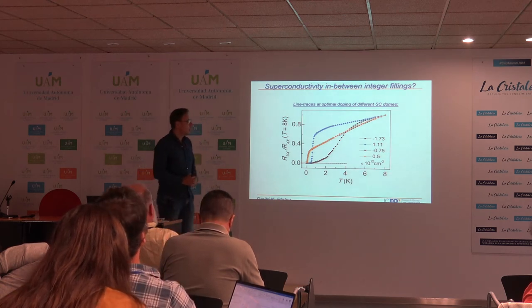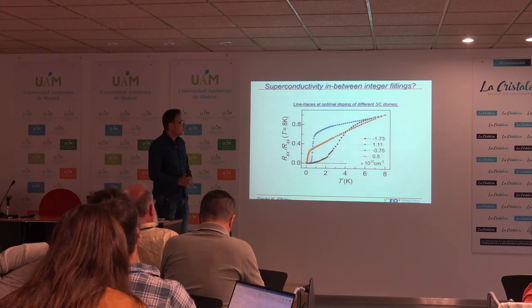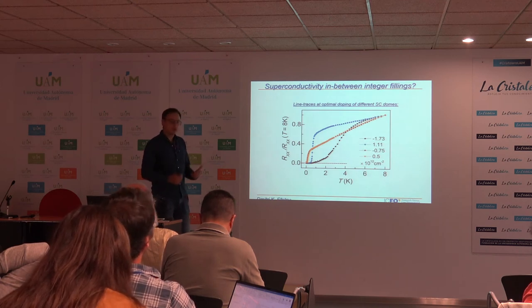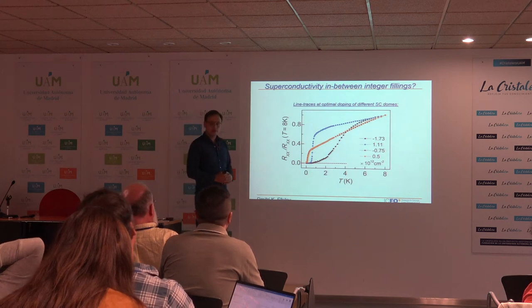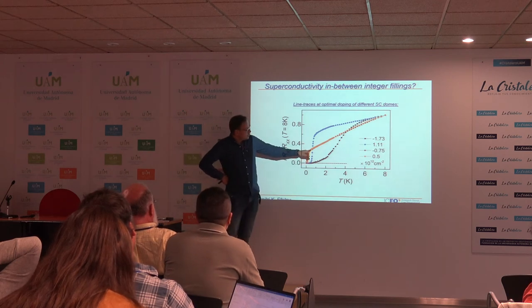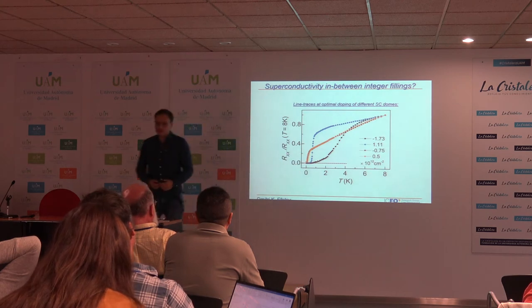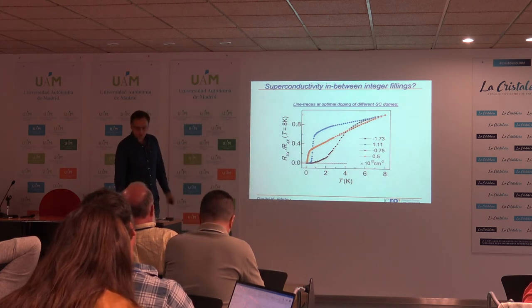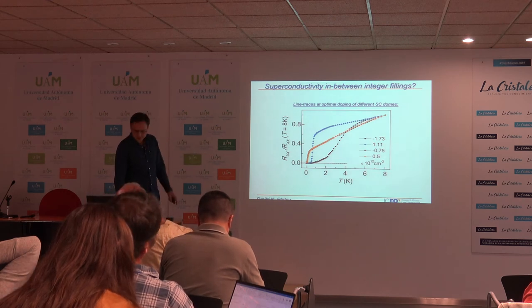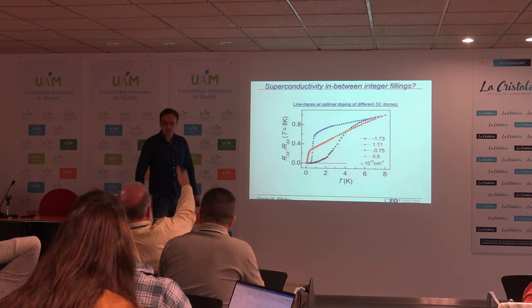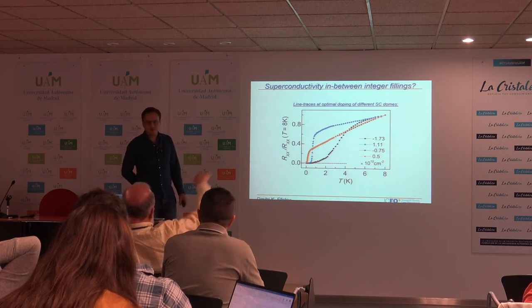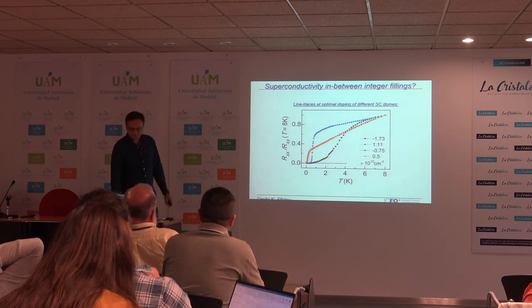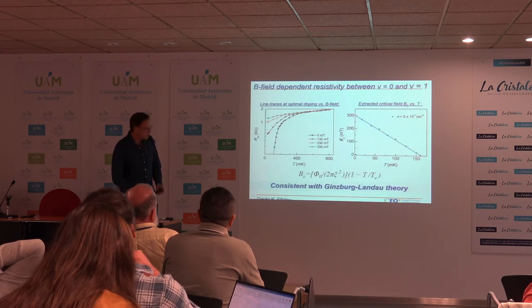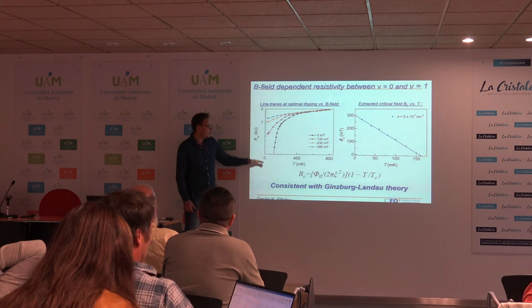And in principle, of course, there are debates whether this could also be electron-phonon interaction, which induces your linear temperature dependence, because this is actually also expected in graphene. But the surprising part is that this linear temperature dependence exists down to 100 millikelvin, where in principle all the phonon effects should be much weaker. So I think in some sense this data also confirms. Is the habit to report the 50%-point line as the TC? Yeah, the 50% point. Okay, so then the other thing, of course, we do, we also apply a perpendicular magnetic field.